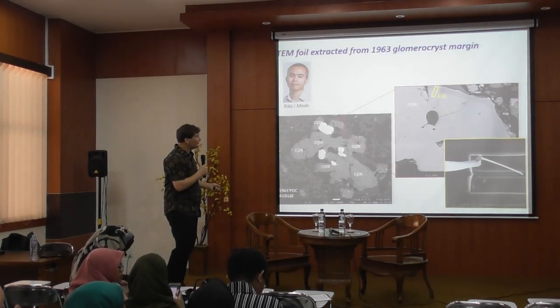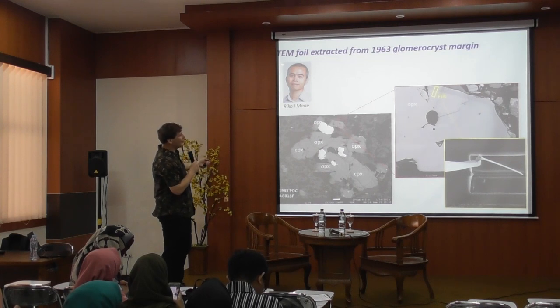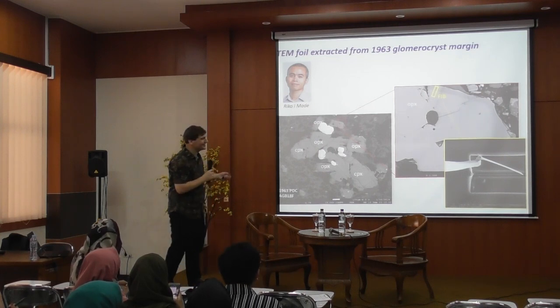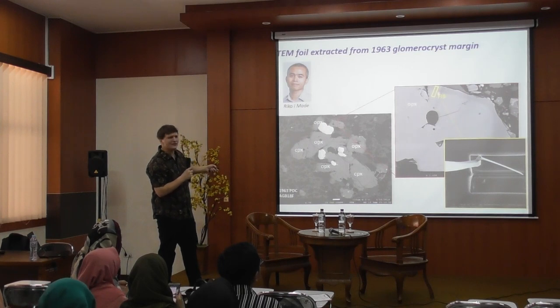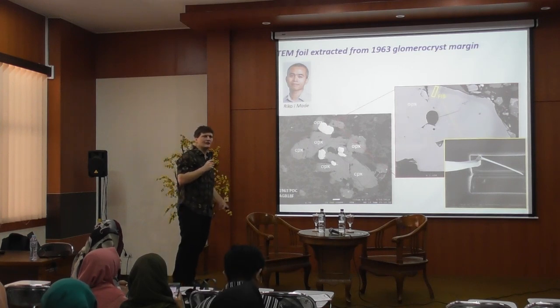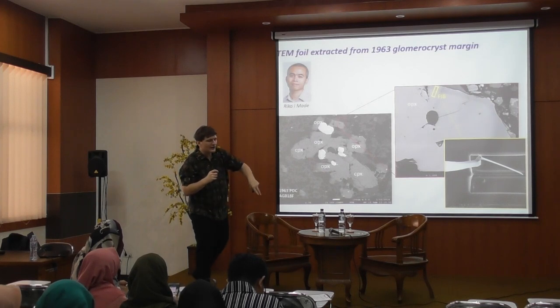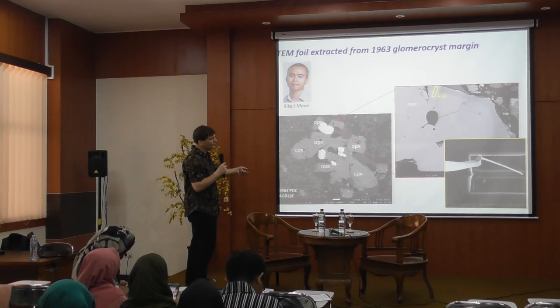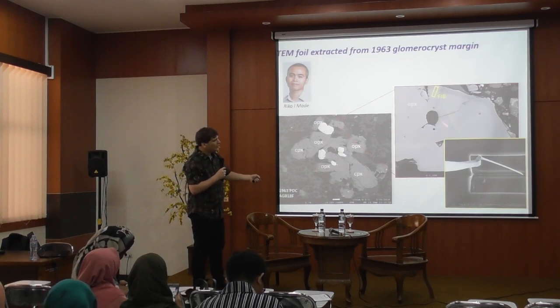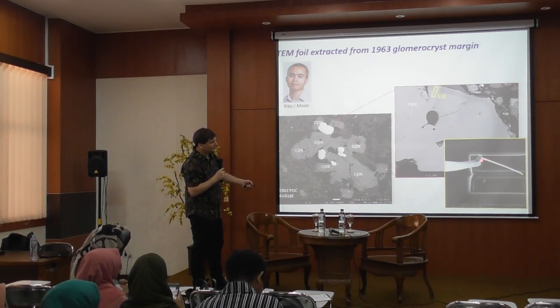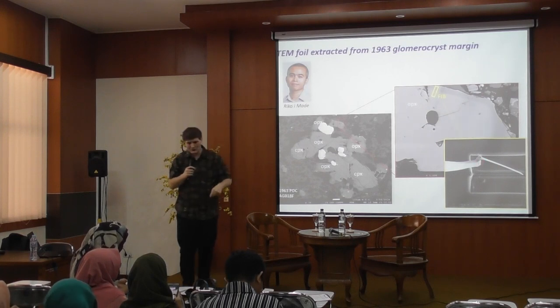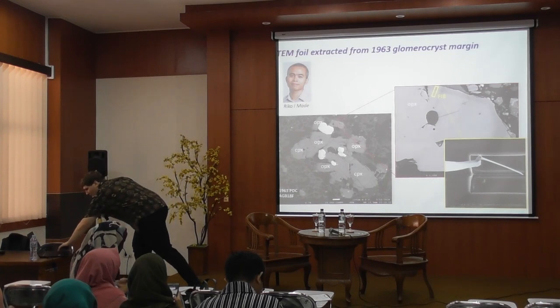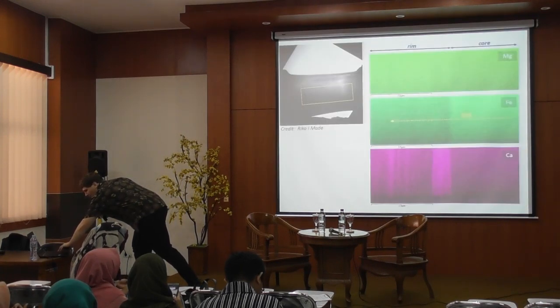And to do that, we have a guy from Bali, actually, who lives in the shadows of this volcano. He used the focused ion beam technique. I don't know if you've heard of this. It's a nanofabrication technique where you can extract small pieces of a sample or carve out different pieces of a sample using an ion beam. So he was able to cut this out and remove this small sample called a foil, welded it to this little needle, and then mounted it so he could look at it on a transmission electron microscope. Here's what it looked like.